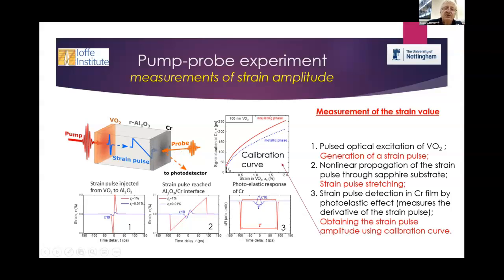We use the photoelastic effect, measuring reflectivity with time resolution. The important thing we use here is the nonlinear properties of sapphire, which are well known, where all parameters are known. If the strain pulse has quite high amplitude, it shrinks - it expands in space and time. This stretching has a well-known dependence on the strain pulse amplitude, and then we may model this stretching - there are some examples.